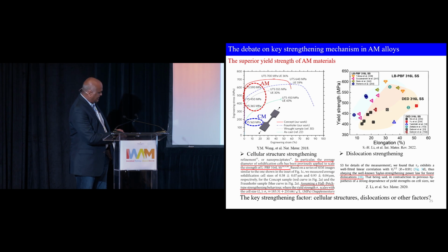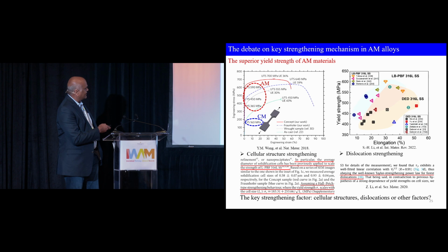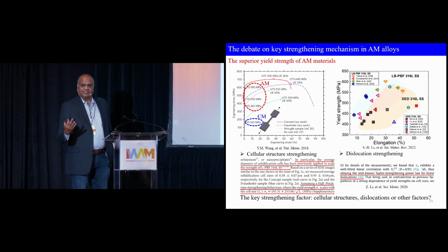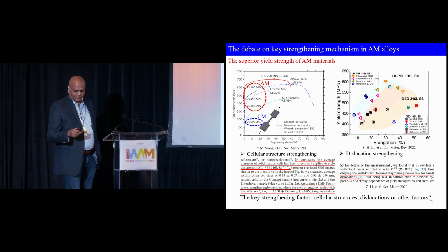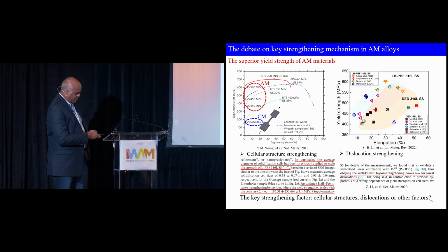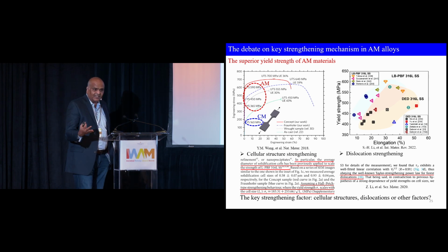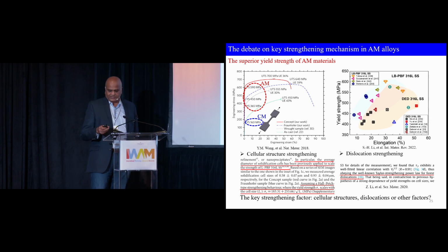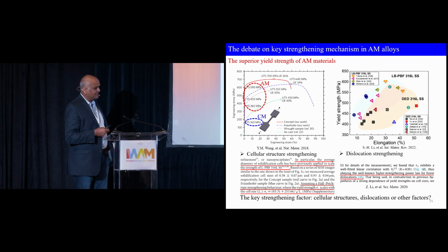So this is the grain Hall-Petch relationship here, and Wang et al. say that instead of the grain size, you fit in the cellular size. The other school of thought says, look, no, you have a very large number of dislocations, and dislocations are the ones which basically hinder plasticity, and that's why you get the high strength.